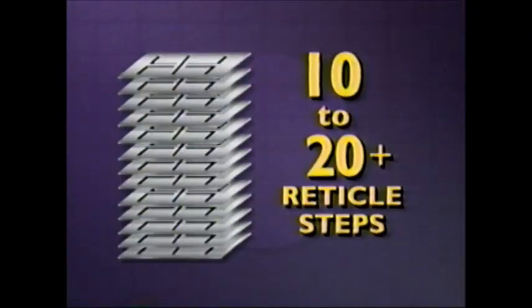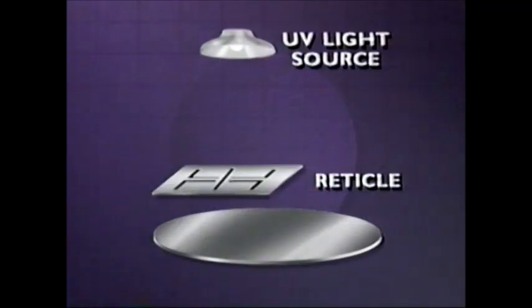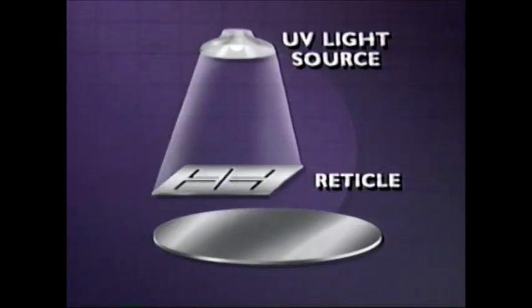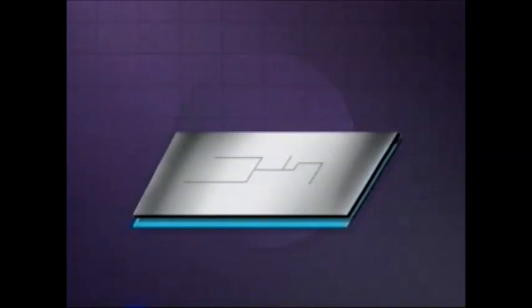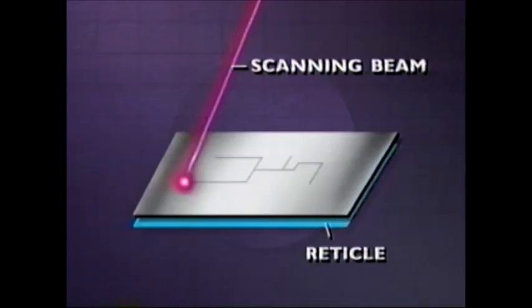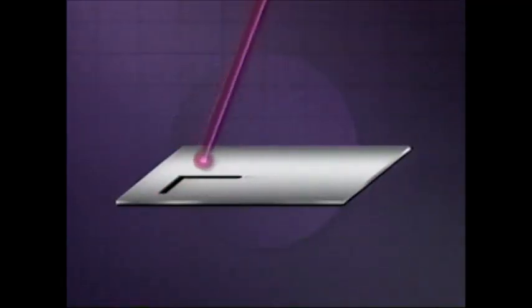Depending on its complexity, the wafer may require from 10 to 20 or more reticle steps to pattern everything from insulated silicon islands to metal interconnects. Photolithography reticles are very similar to photographic negatives inasmuch as they allow light to pass only through those areas from which the reticle material has been removed. They are made by etching a thin metal sheet or metal-coated glass using an electron beam. This beam operates like the beam in a television tube. It moves back and forth, scanning a pattern on the blank reticle.